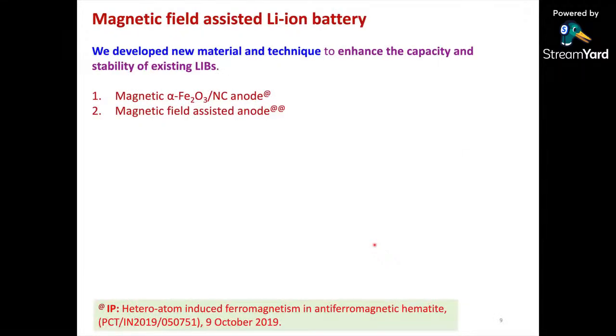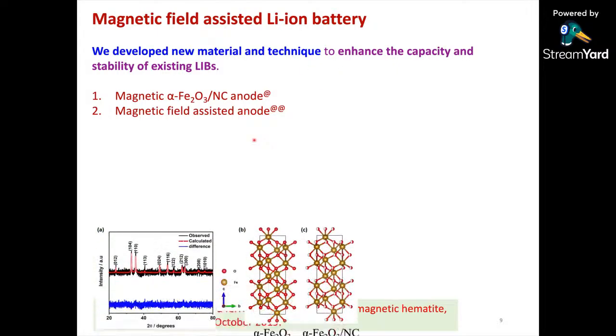Okay, so first I told you how to enhance the capacity and stability of the existing lithium-ion battery. We have used magnetic alpha Fe2O3 nitrogen-doped carbon as an anode. I will show you the synthesis process and why it is special compared to normal commercial alpha Fe2O3. The commercial alpha Fe2O3 is antiferromagnetic, so we can make it into a ferromagnetic material so that the magnetization can be enhanced nicely. Using this anode and a magnetic field of almost 0.15 Tesla, it is possible for us to enhance the capacity as well as the stability.